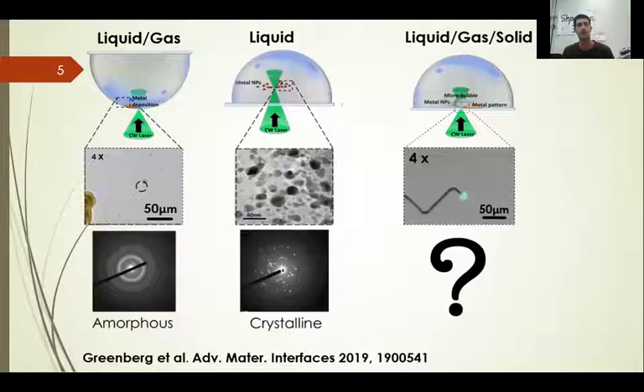The first case is when the laser is focused on the edge of the metal ion solution droplet, at the liquid and gas interface. And as we can see, we get a deposition. We took this deposition to the high resolution TEM to analyze its nanostructure, and we found that the nanostructure of this deposition was amorphous. The next case is when the laser is focused inside the metal ion solution droplet, at the liquid interface. And as we can see, we got metal nanoparticles. We also took those metal nanoparticles to the high resolution TEM to analyze their nanostructure. And now we found that the nanostructure was crystalline.